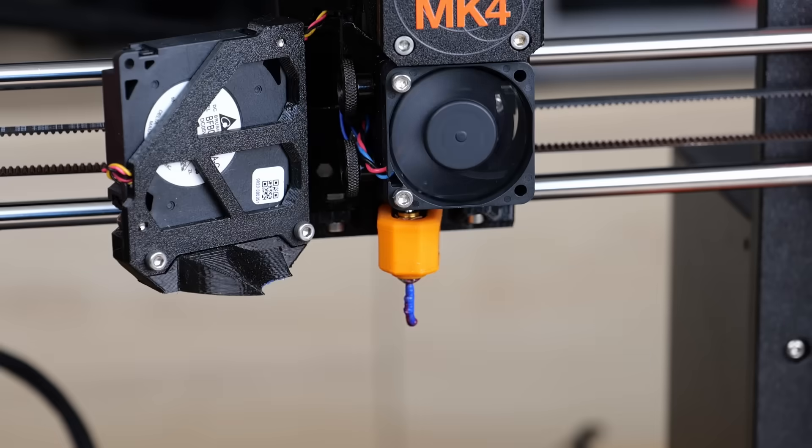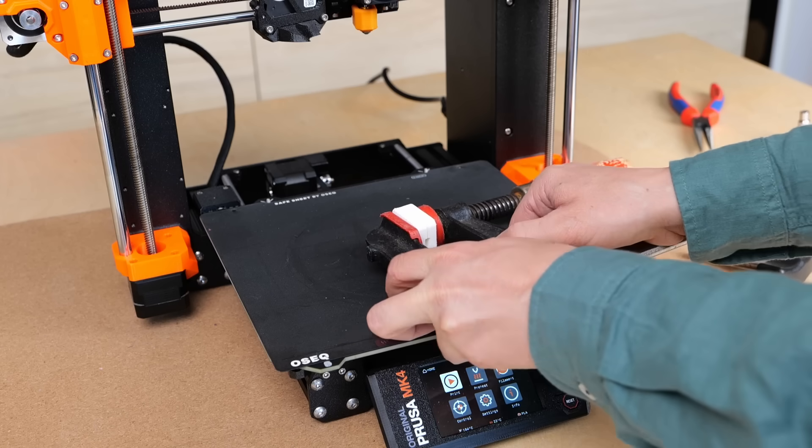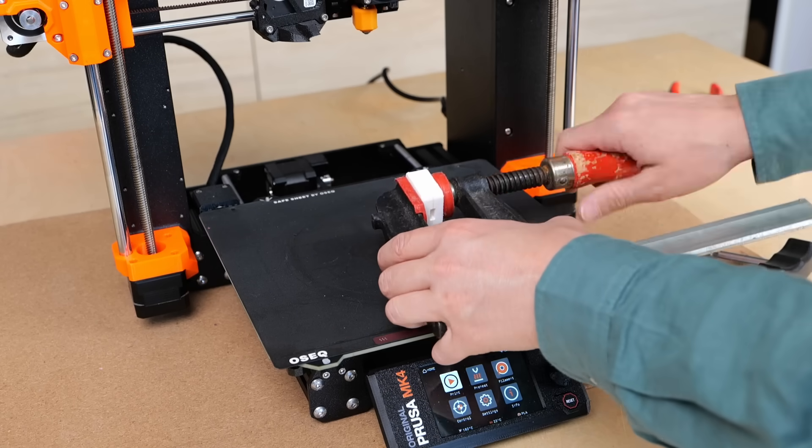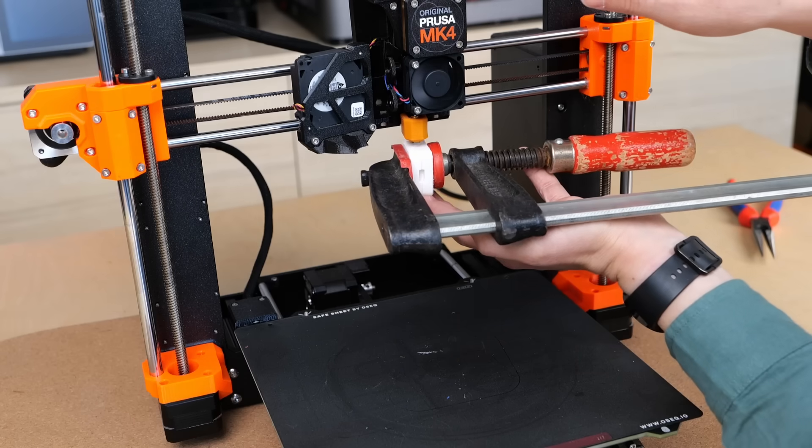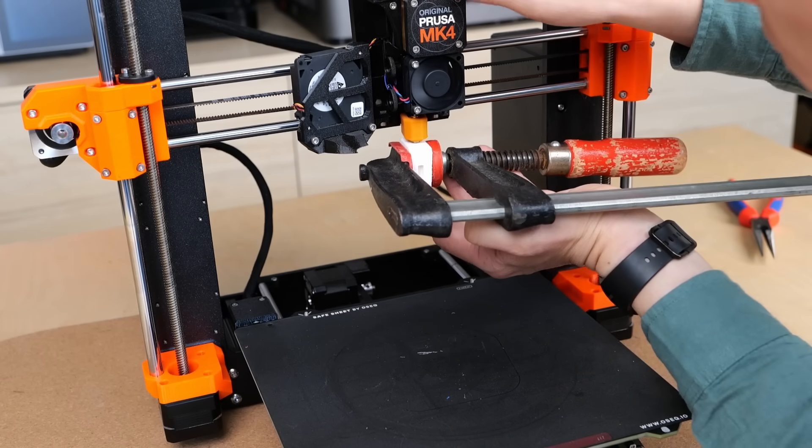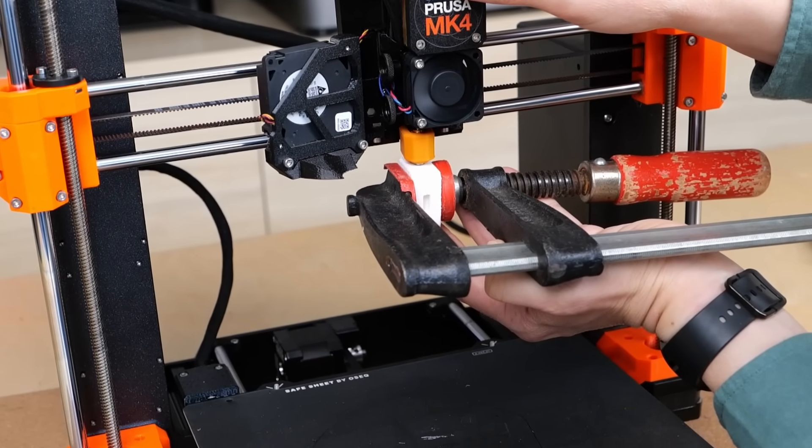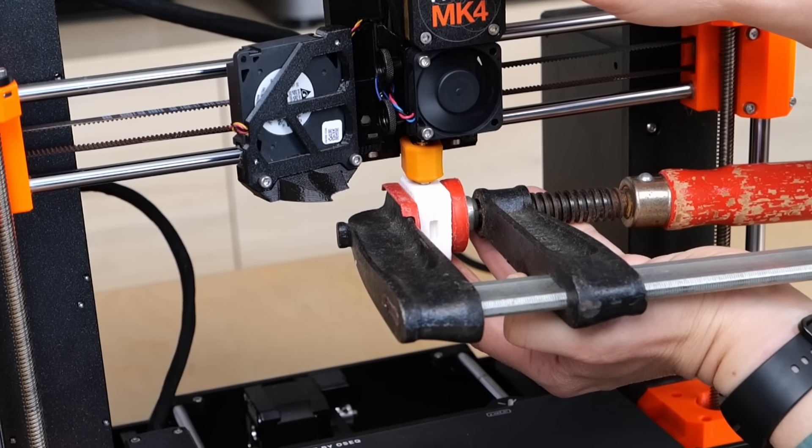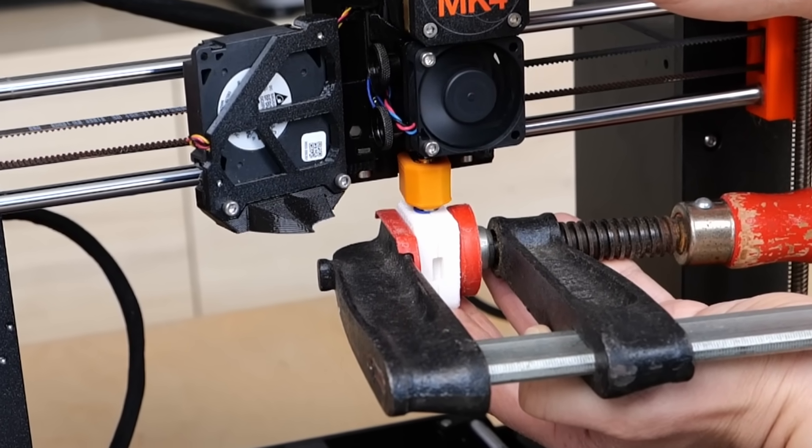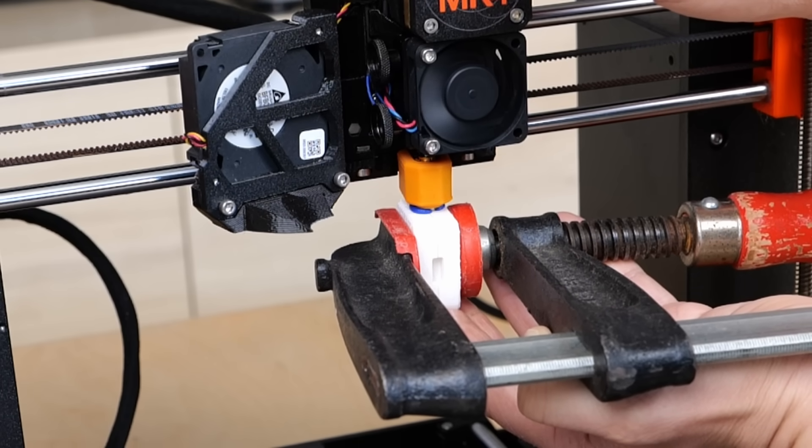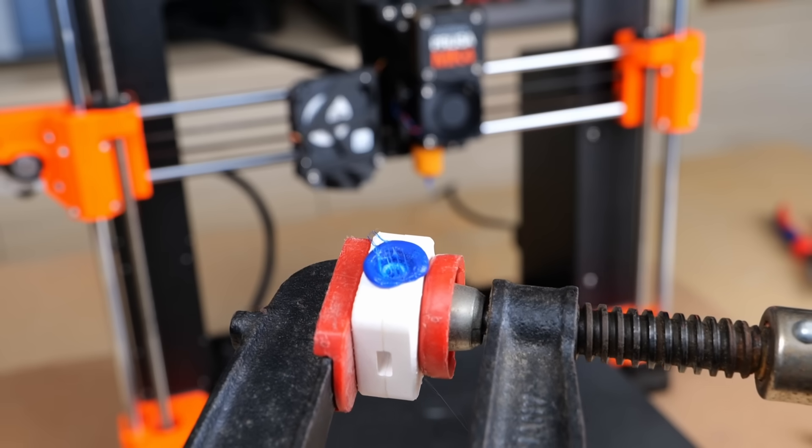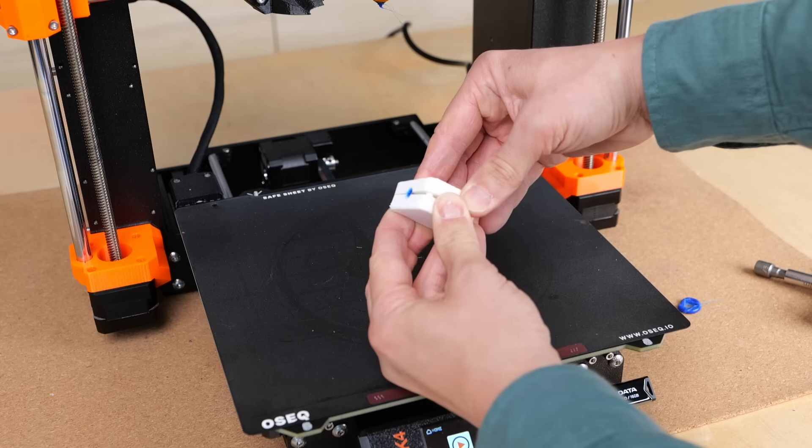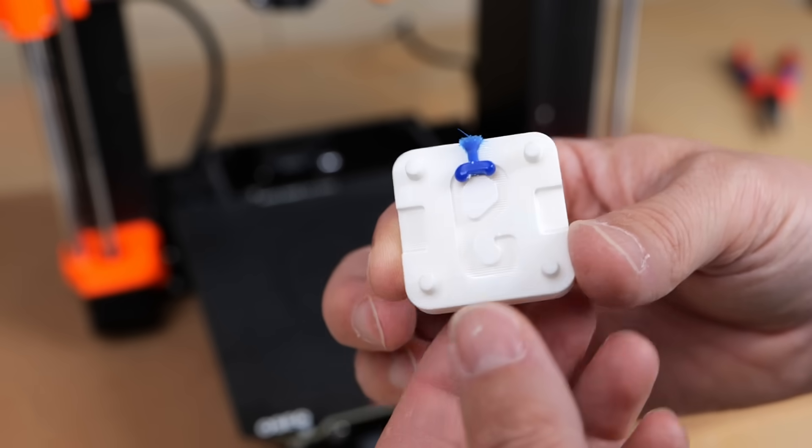Let's do the first shot. I loaded some regular PLA into the extruder. Then I clamped the mold with screw clamps in order to make sure that no plastic can seep through any of the gaps causing flashing on the parts. I heated the hotend and then started to inject the plastic. After a short while I noticed that the PLA was leaking out of the side of the sprue. This could either mean that the mold filled up all the way or that the mold got blocked quickly. Opening it was very underwhelming because the plastic barely flowed into the cavity.